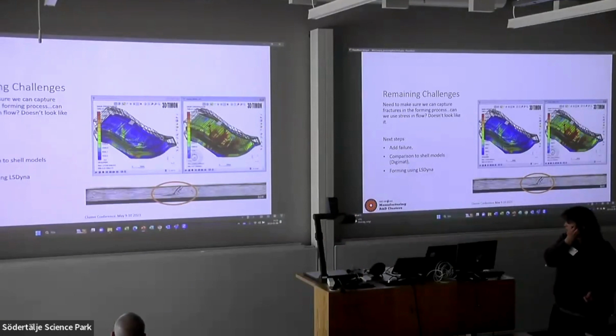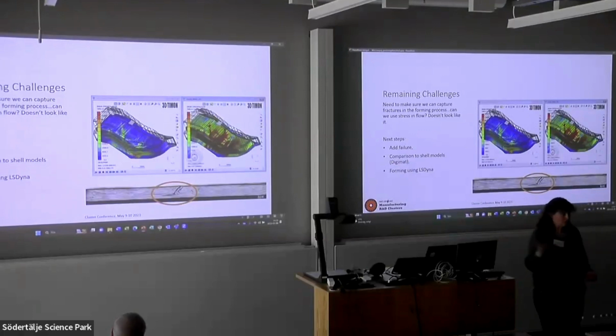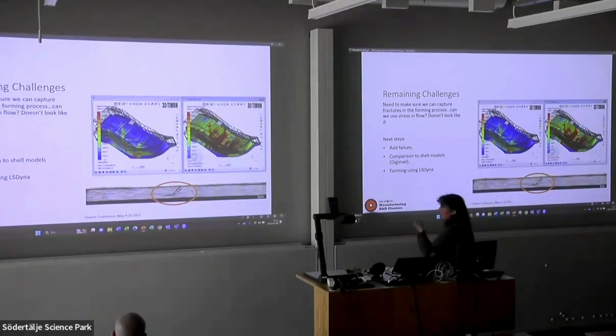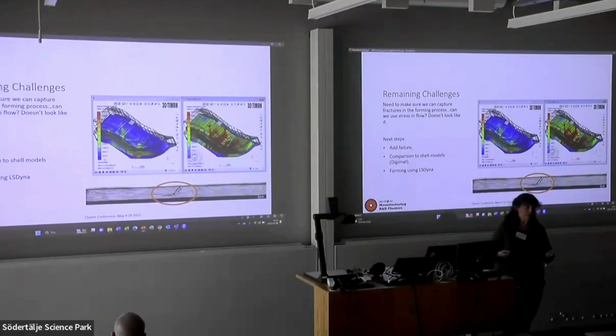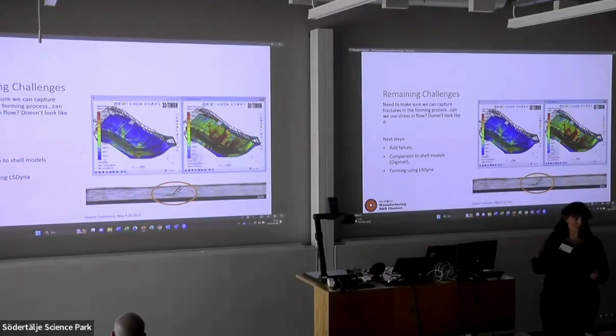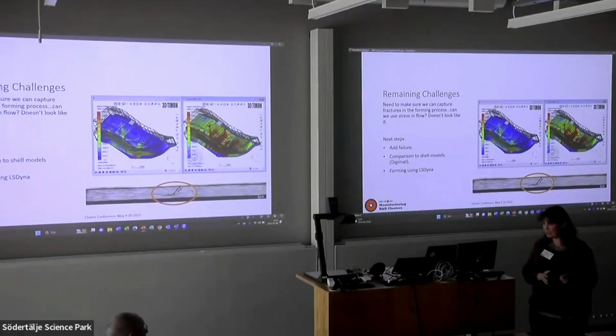And the other thing that we're doing is looking to see whether we can do this using Dyna all the way through, even in the forming process. And there, I think we might have a better chance of capturing this tearing behavior and moving behavior when we're no longer modeling it just as a fluid. We're going to compare it to the results from the shell models, but I already know the results from that. The shell models are much better if you use Digimat. That's not surprising, because you calibrate the final material.